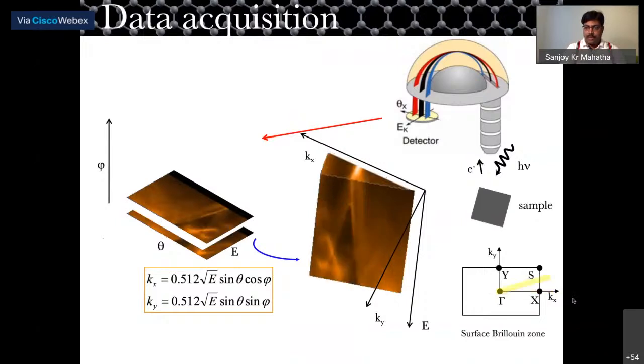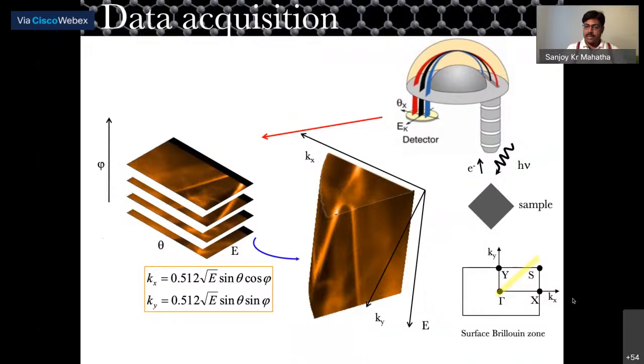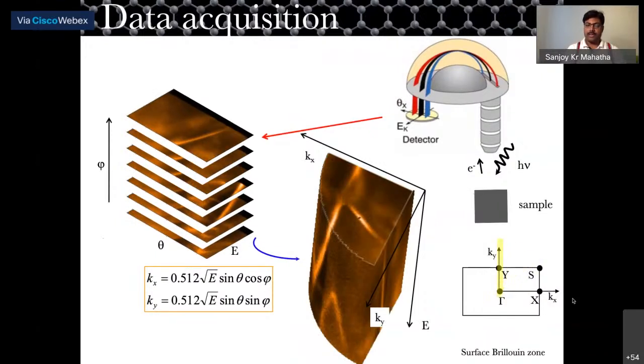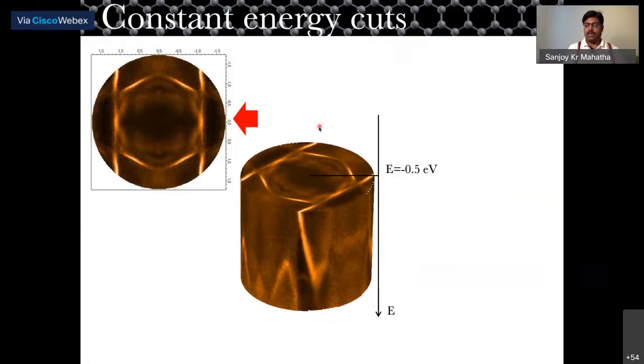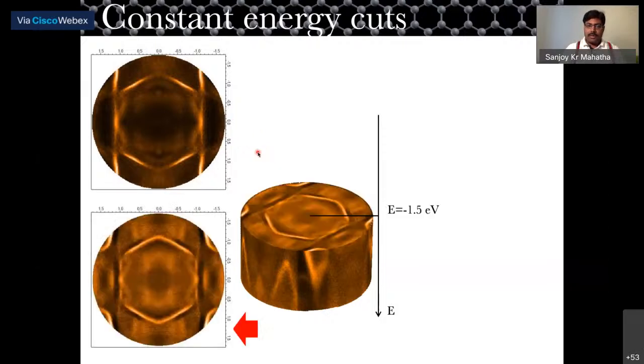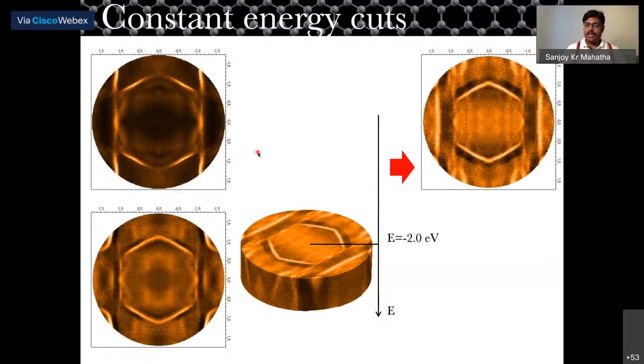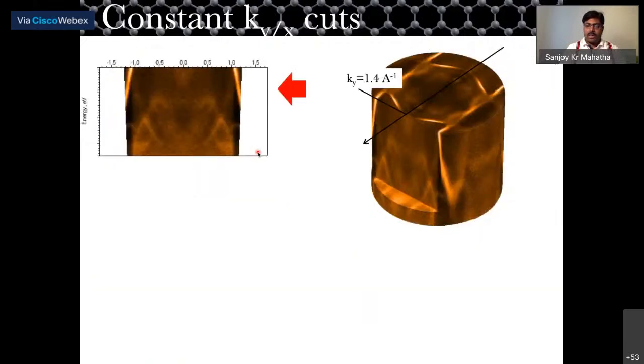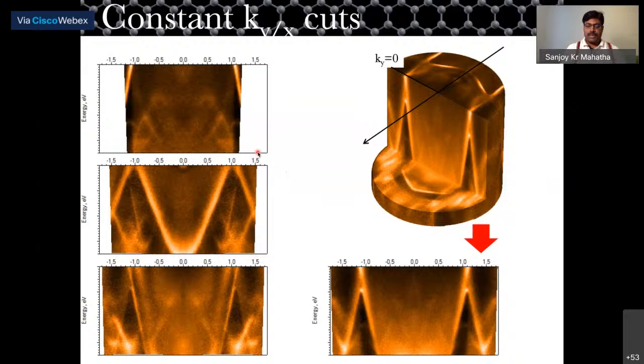And then by rotating the sample, we can acquire different slices, and we can make this sliced three-dimensional data stack. And then by symmetrizing the whole data set, we can make a three-dimensional data set or a data cube. This data can be cut at different energies to see what the constant energy contours look like. Or we can also cut at different kx or ky to see the topology of the band, how it is changing along orthogonal directions. Okay, so this is what we do in angle resolved photoemission spectroscopy.